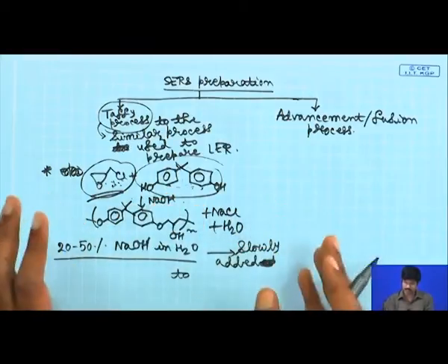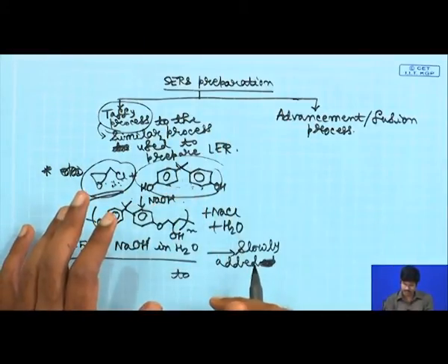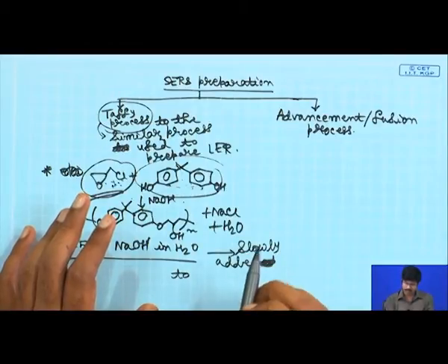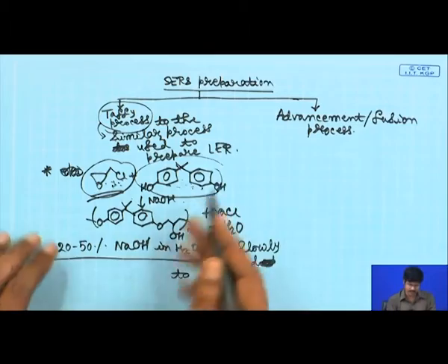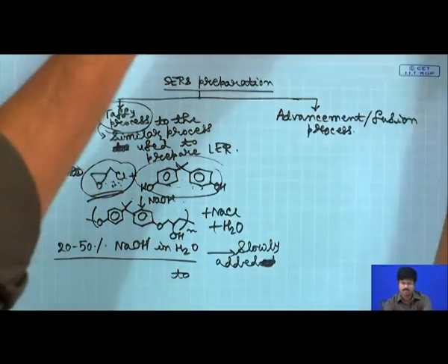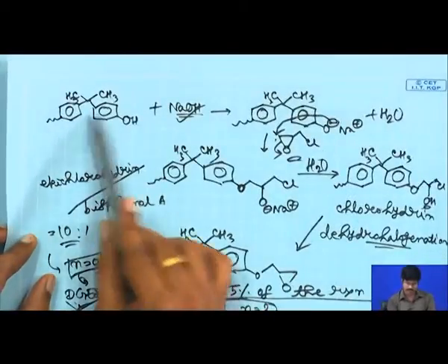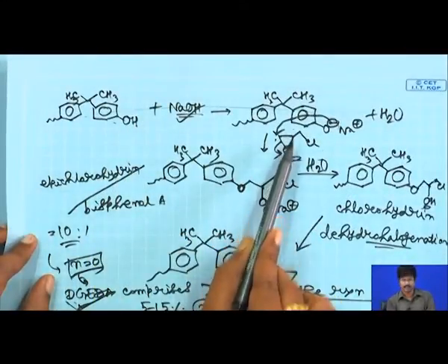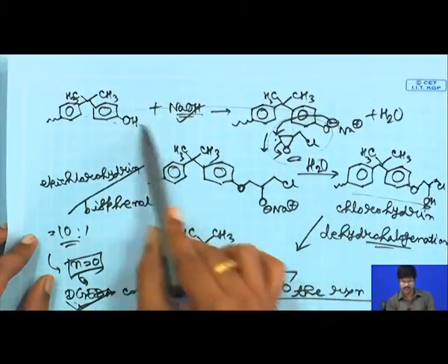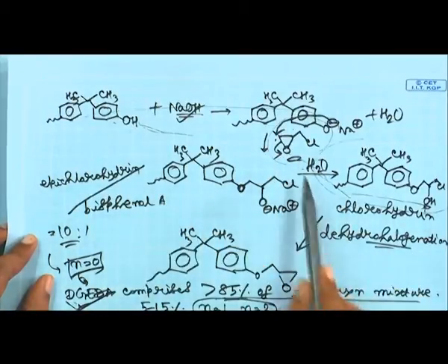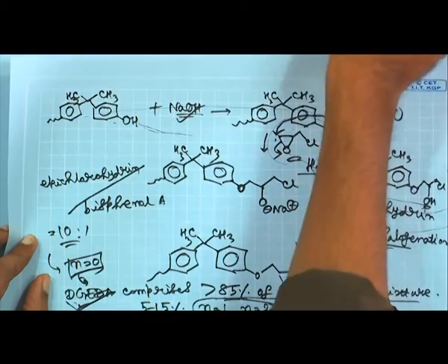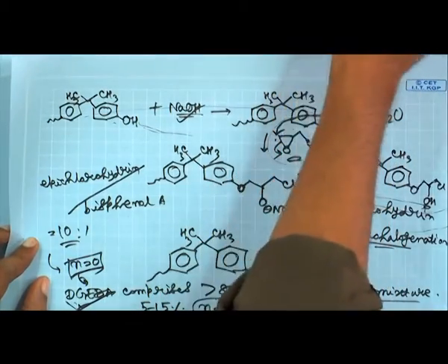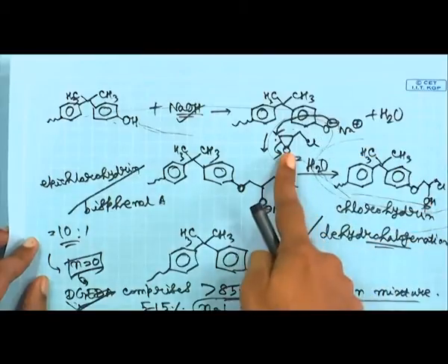So, this coupling reaction proceeds during the initial stages, a highly exothermic reaction, and we talked about the coupling reaction, it produces your chlorohydrin. So, this is your coupling reaction. First it will be deprotonated and then that reacts with epichlorohydrin to produce a chlorohydrin. So, in the initial stages you will get this chlorohydrin. As the reaction proceeds further and further, this dehydrohalogenation will become predominant. All right. So, that is the overall process. You are adding sodium hydroxide aqueous solution to a mixture of your epichlorohydrin and bisphenol A.